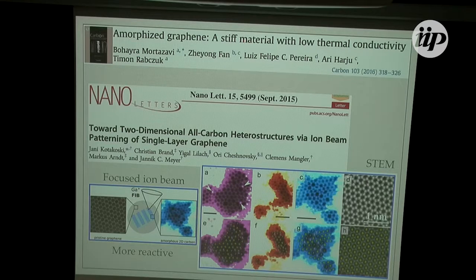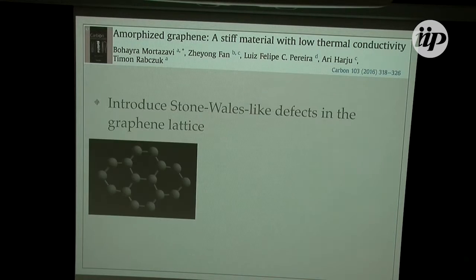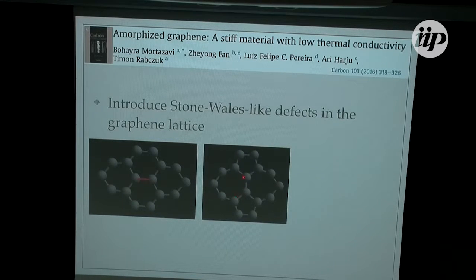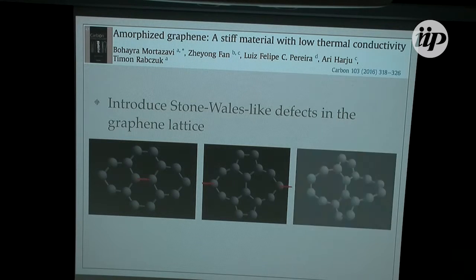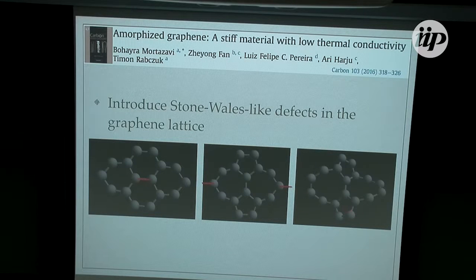And then what we thought was, okay, let's look at what about the thermal conductivity and the mechanical properties of this thing. Now, first thing we have to do is to amorphize our graphene in our computer, right, in the simulation. And our way of doing it is introducing Stone-Wales-like defects. So Stone-Wales defects are 90-degree rotations of a bond in the graphene sheet, right? So, for example, if I have this bit here, these 4 hexagons, if I rotate this bond here, I end up with something like this. Now I have 2 pentagons and 2 heptagons. And I could rotate, again, another 2 bonds here. And then I end up with octagons and pentagons and heptagons and all sorts of carbon polygons, right?